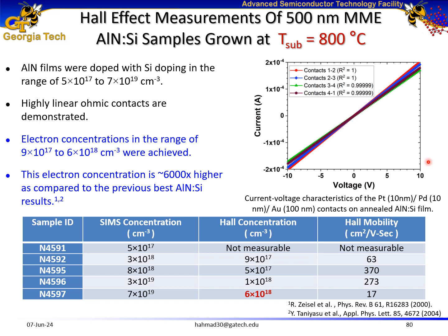So I utilized the high crystalline conditions of MBE, and I grew silicon doped aluminum nitride films in the doping range of 5 × 10^17 to 7 × 10^19 per centimeter cube, and I achieved a high electron concentration of 6 × 10^18 per centimeter cube, which is 6,000 times higher as compared to the previous best electron concentrations in silicon doped aluminum nitride.